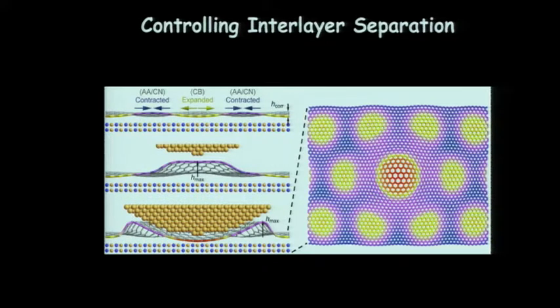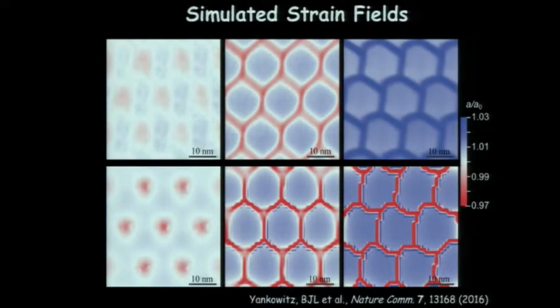So this is with the tip, it's this position. Here, the graphene lattice becomes slightly strained underneath it, and so we see a longer lattice constant when we press down hard than when we're either far away or if we could do the measurement without being there. And so these were calculations here showing the expected strain field that you should get in these different imaging conditions. These are our experiments here. These are the calculations of what you should expect to see.